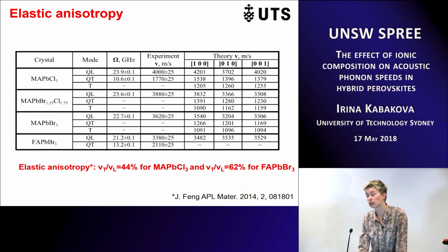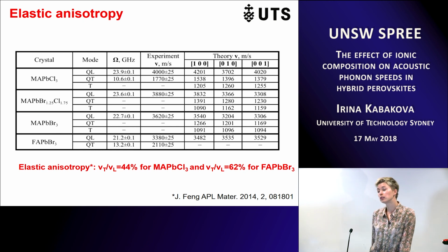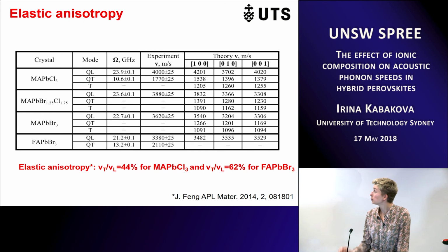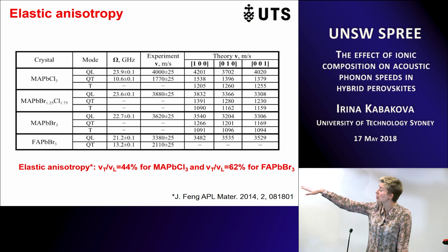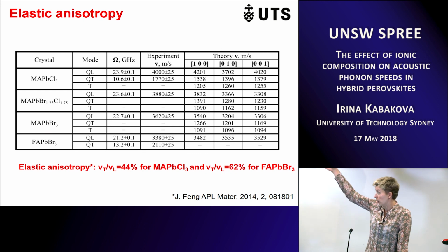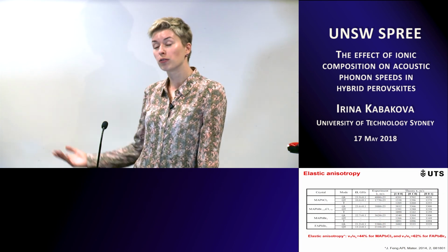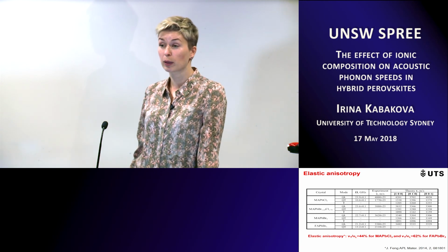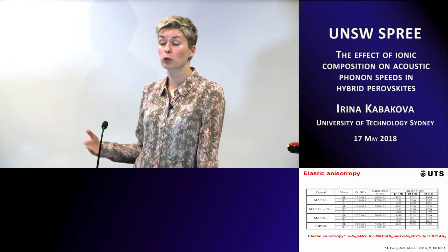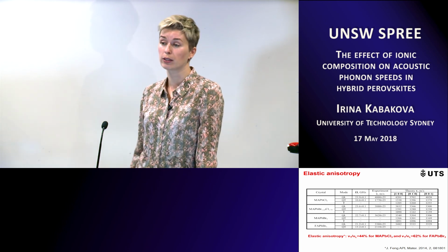It's a bigger gap. That would seem to make sense, yes, because the halide has to do with the bond strength, essentially, and so that's going to be changing much more dramatically than the symmetry change in the organics. I guess the combination of the two can make a very big difference. Yes, and you can see that, for instance, from the first crystal at the top. The difference is substantial. It's more than 20% in elasticity, and it would affect charge mobility by 20% as well. So then you can draw some recipes for how to improve charge mobilities based on that.